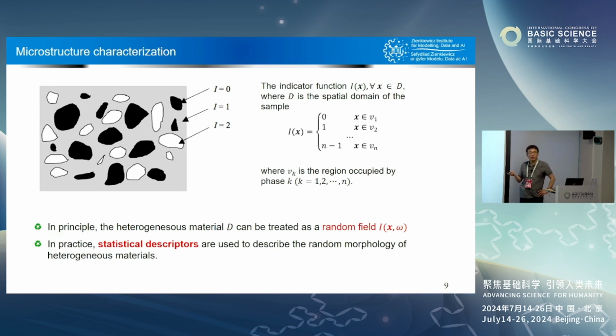To capture that random field just in 2D, you run out of your mathematical representation capacity, unless you start to introduce assumptions. Let's say if you say the whole field is Gaussian, then you only need two parameters. But that's a very rough, very brute assumption. No material is Gaussian for a fact. So in practice, what engineers and researchers have been doing for 50 years, perhaps longer, is instead of worrying too much about the random field, they introduce so-called statistical descriptors to capture, in a quantified manner, the features of